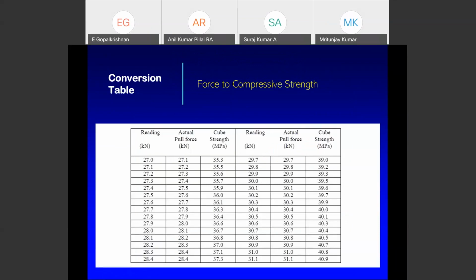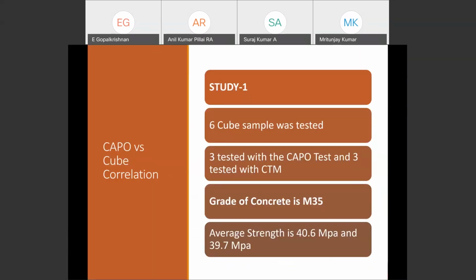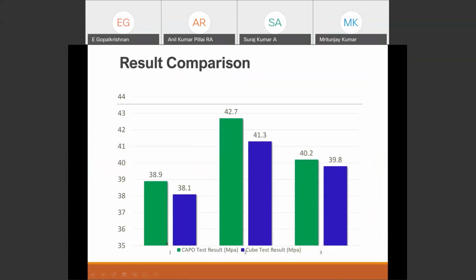This is all given by the manufacturer as per ASTM C900, but I wanted to believe it myself, so I have done a couple of studies. I cast cubes of M35, and I compared the results of the CAPO test and pull-out test on the same cube as well as the same group, and I did the compressive strength conventionally, so that I can get closer values. So you can see the value is very, very acceptable, very close. This is one of the things.